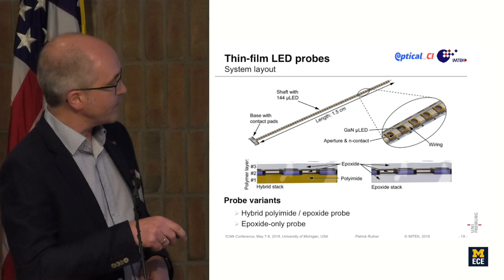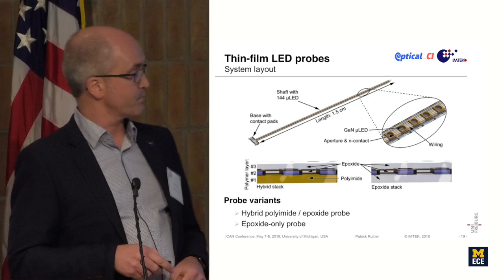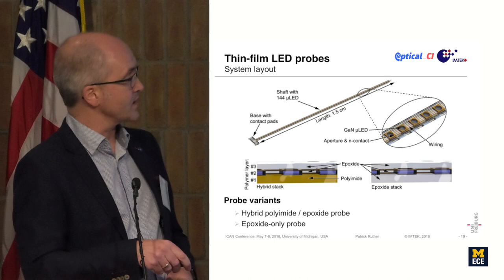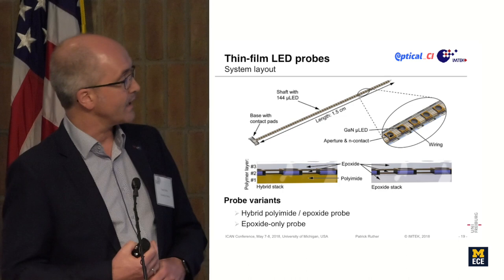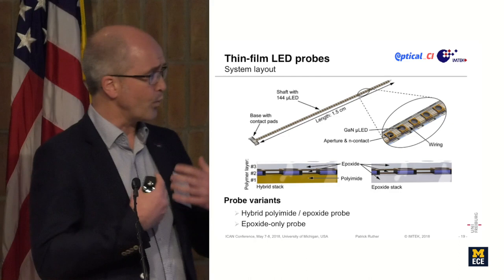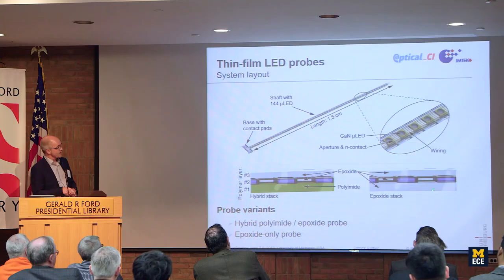And we have two flavors of this probe. One probe here comprises a polyimide substrate and epoxy on top, encapsulating the LEDs and the metal tracks contacting this device. And then we have the completely epoxy-based probe where we can show, and I will show you the pictures, where we can improve the thermomechanical behavior of the device itself.